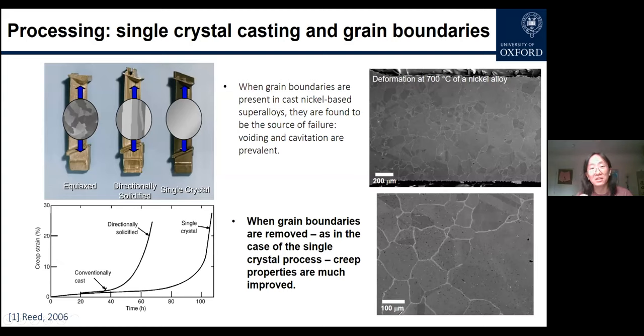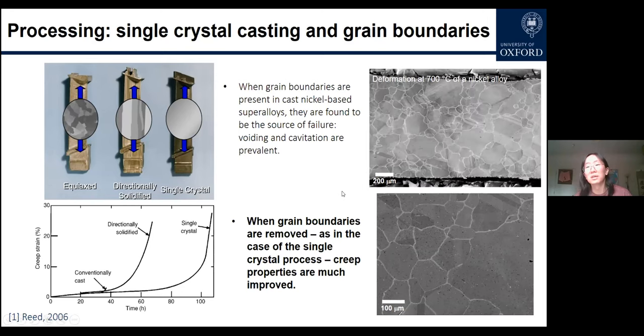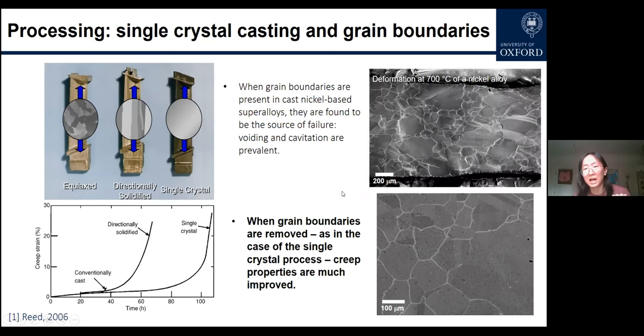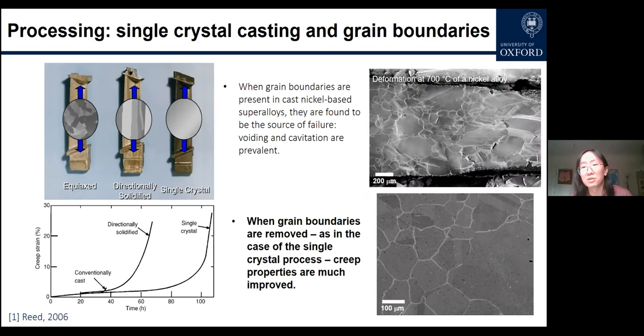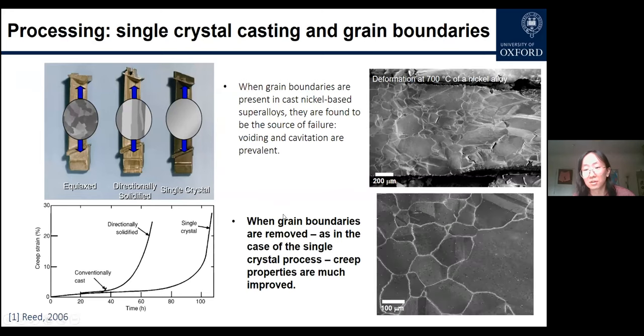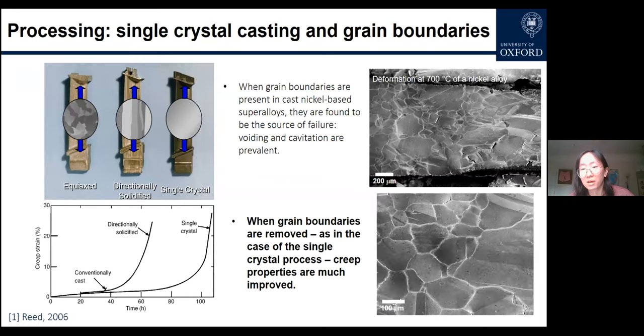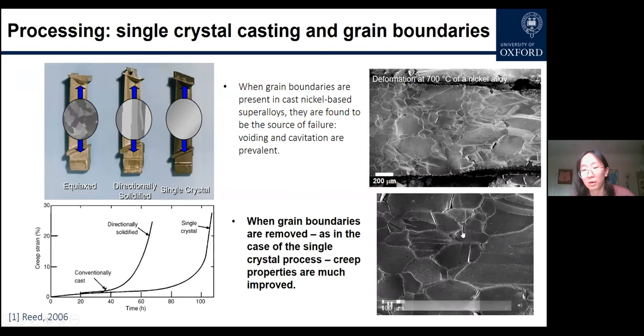And the reason for that is we don't like grain boundaries very much at high temperatures because they are the source of failures. Voids and cavities are quite prevalent, and I can show you here one of my experiments on a nickel alloy, in situ SEM, deforming this alloy at high temperature, which is around 700 degrees C. You can see all those failures are along the grain boundaries, and they are basically linking up and causing problems. This is a slightly higher resolution of the same experiment. You can see how they developed as you pull it.